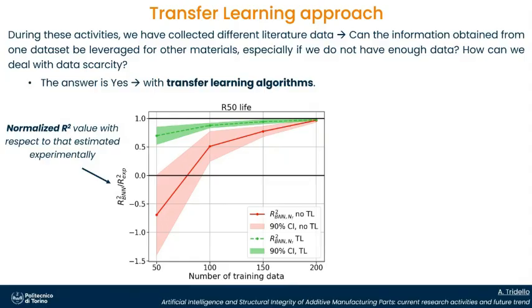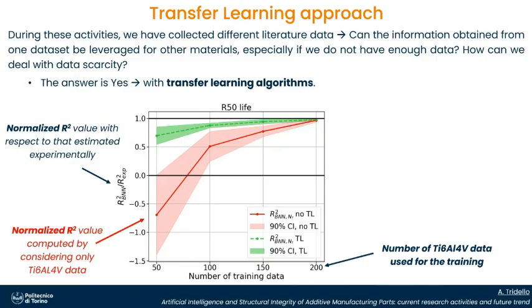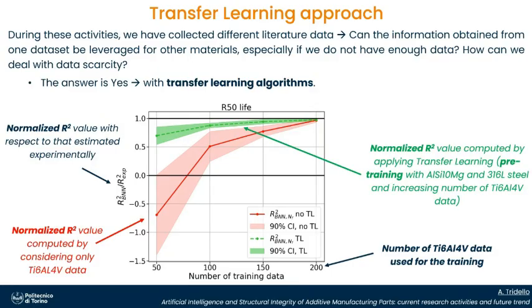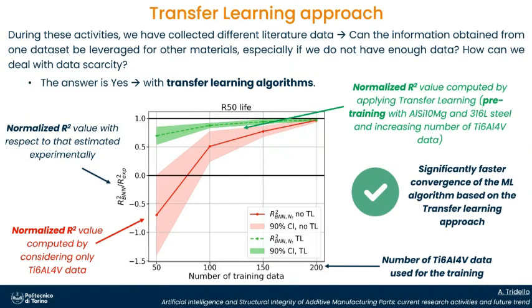Here you can see the normalized R-squared value with respect to the experimental one for a specific data set. Here we have the number of titanium data from 50 to 200. And here we have the normalized R-squared value computed by considering only the titanium data, from 50 to 200 data. And here we have the normalized curve computed by applying transfer learning, so pre-training with aluminum and steel, and increasing the number of titanium alloy data. You can see that we have a significantly faster convergence of the machine learning algorithm based on the transfer learning approach. So if we use transfer learning, we can obtain, even with limited data, a good prediction.